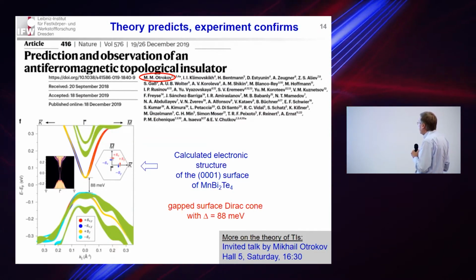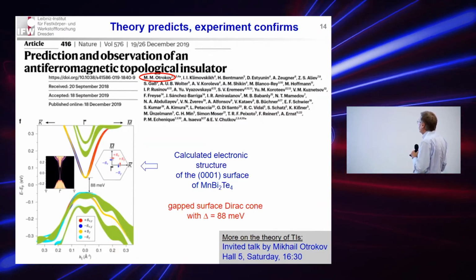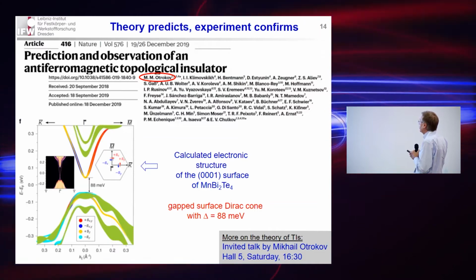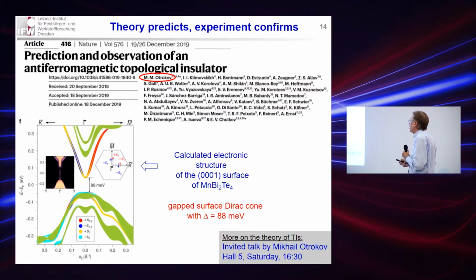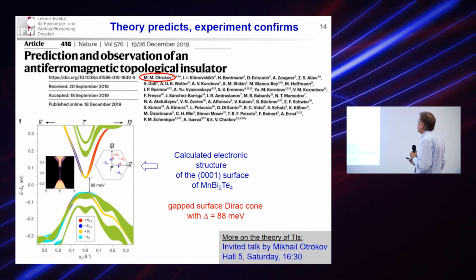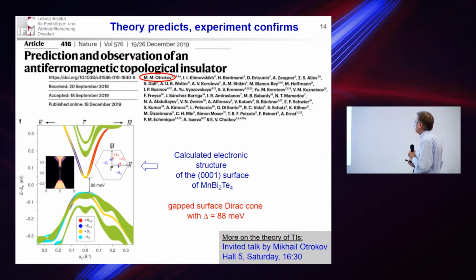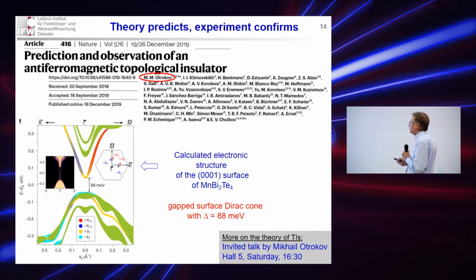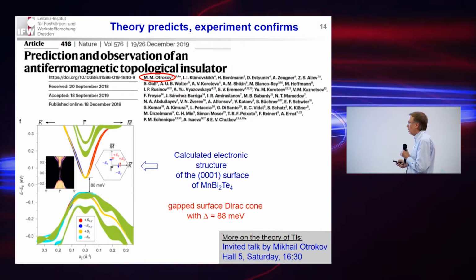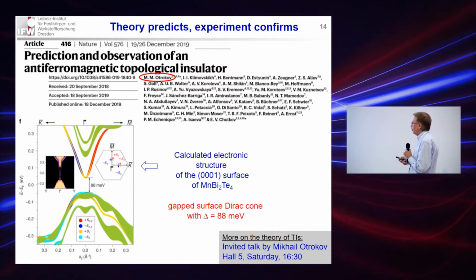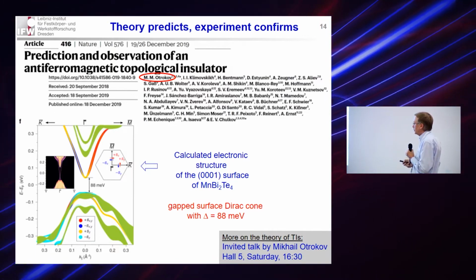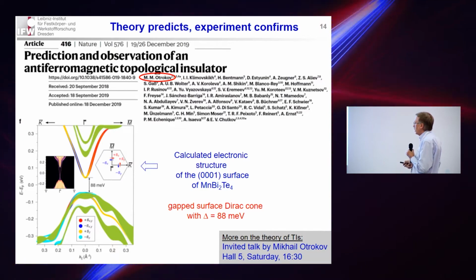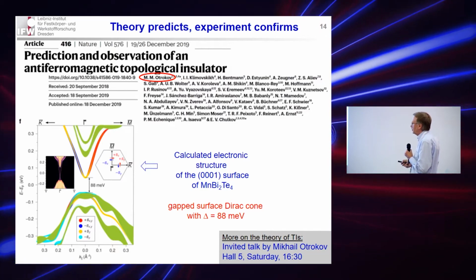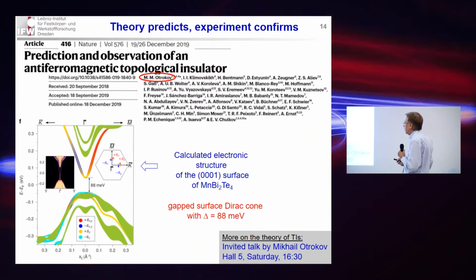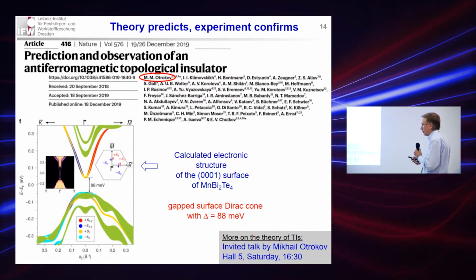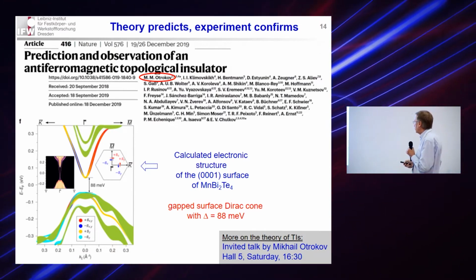first of all, a theoretical prediction in the group of Evgeny Chulkov, where the main player was Mikhail Otrokov, who predicted that in this manganese bismuth tellurium 2-4, indeed, a non-trivial topological electronic structure on the surface can be realized. These are surface Dirac cones, and they exhibit a relatively small gap of about 88 millielectron volts, about 90 millielectron volts in the magnetically ordered state.